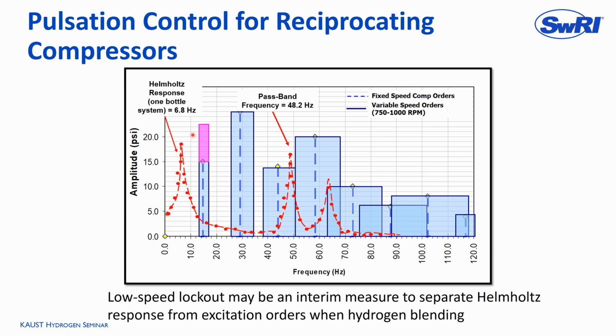frequency response of the pulsation filter positions the frequency quite low, below the operating orders. So 1 times running speed, 2 times running speed, etc. of the recip compressor. The blue bars around those running speeds just reflect that many recip compressors run at variable speed. Typically you don't ever want these to overlap, otherwise you'll end up with severe piping vibrations. As you move that speed of sound up for hydrogen, the same design of an existing acoustic filter will move up, and you run into areas where those frequencies may overlap.